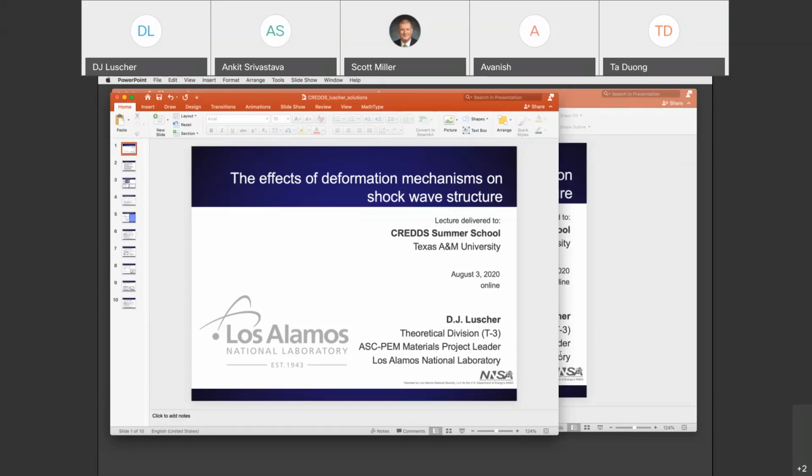But then what we have is all this damage. The specific question was the glass that's breaking. Well, once that wave hits the surface of a glass window, it's imposing that pressure state on the glass. And if you impose a significant enough pressure on a glass window, you're going to break it. Now, the mechanism of fracture within the glass is not due to a purely hydrostatic state. By applying this pressure to the surface of the glass, you could think of just applying a pressure to a plate or a shell, right?